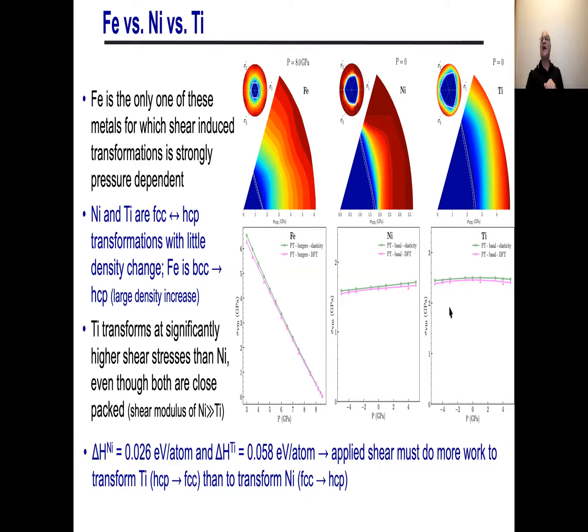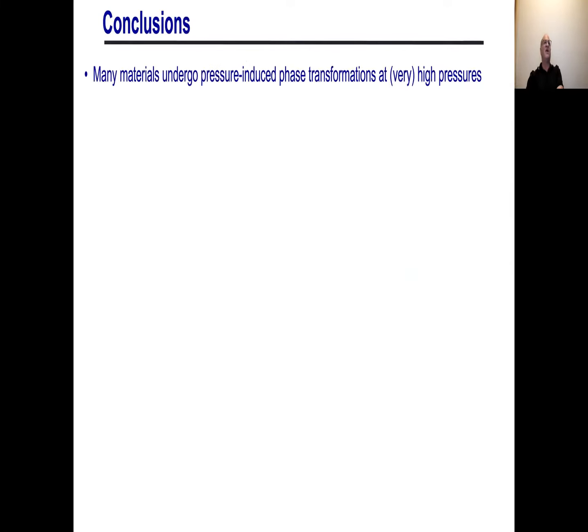HCP titanium to FCC titanium than I need to go from FCC nickel to HCP nickel. So again, that ordering is consistent with the experiments. I mean, with the DFT calculation. Then it makes sense. Okay, so let me conclude.